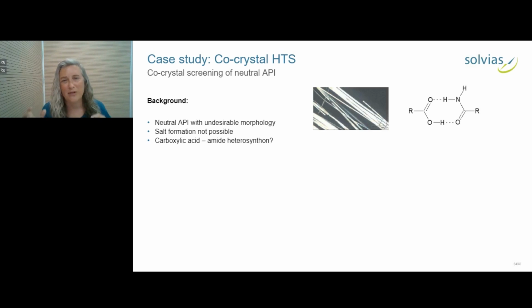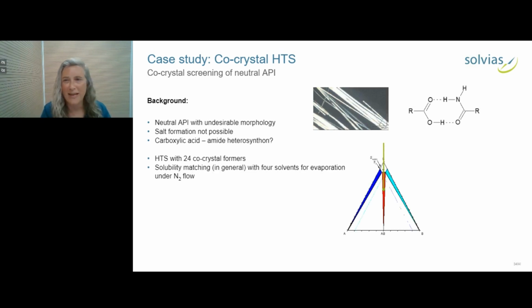But there was an amide group, and there is the possibility, and that's shown on the right here, of perhaps making a heterosynthon. So we might be able to couple it to some carboxylic acid. And there were other interactions we looked at as well. So we selected 24 potential co-crystal formers and did a high throughput screening. And the first screening was done by mixing roughly and evaporating from 4 solvent systems. And evaporation is very good when you have a symmetric phase diagram. So when the solubilities of the two components are similar in the solvent, then that gives you a good way to access the co-crystals. And we then analyzed the products by Raman microscopy.